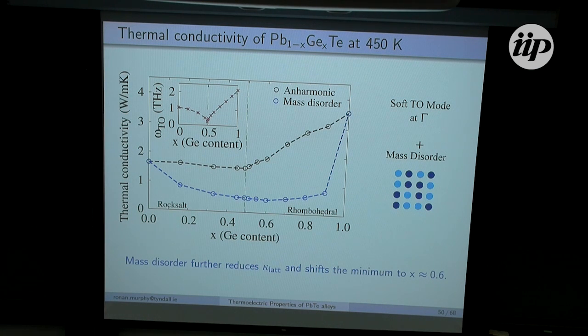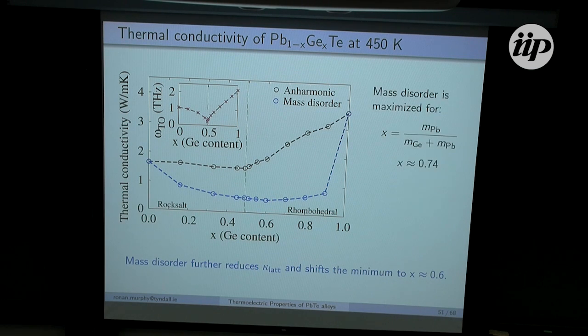Now there are a couple of things happening here just to draw your attention to. So if we take a look here at the phase transition along this green line, see the minimum value here. However, we see that the minimum value, when we take mass disorder into account, happens about here. Now, if we take the formula for mass disorder and differentiate it, we find that it's greatest for a composition of about x equals 0.74. So what's happening here is the phase transition wants to minimize thermoconductivity here, and mass disorder is acting to minimize thermoconductivity at about here, and while they compete with each other, they eventually compromise, and we see this minimum thermoconductivity at about here, 0.6.